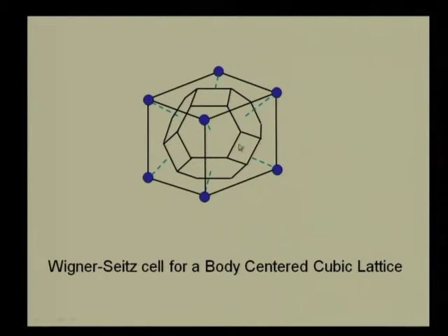For example, this structure that you see here is part of a plane that bisects the line joining the body center of this single cube that you are seeing here and the neighboring body center. So if you had continued this lattice, if you had drawn the next set of lattice points here, you would have once again found one other body center. So you can connect the body center of this particular unit cell to the next unit cell, and the perpendicular bisector of it will actually be this plane, right, simply because the body centers are exactly halfway into the unit cell.